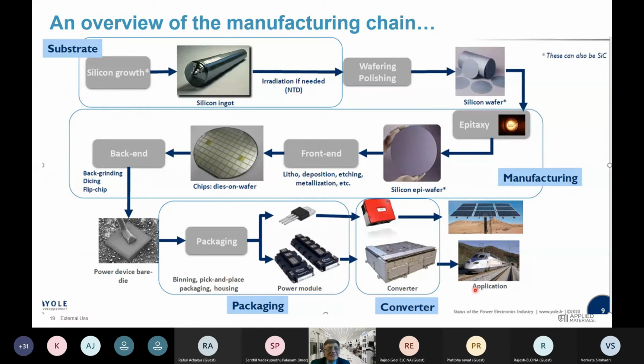So what is the manufacturing chain? I have covered a part of it before, but as a snapshot, just sharing what is here: you start with an ingot, you slice it off using an appropriate exfoliation process, which could be laser or wire saw, and you lap and polish it to create that wafer. And then in our wide band gap manufacturing, on that base substrate, which can be silicon or silicon carbide, you do an epitaxial coating. Okay, so you grow a thin layer of gallium nitride or a thin layer of some wide band gap semiconductor on it, and then you start processing it.